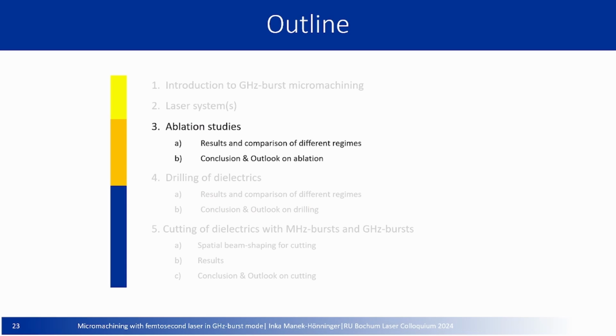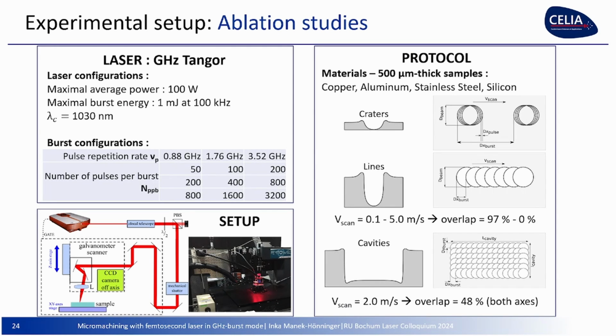Now, the ablation studies that help us to deduce what is happening, that I showed you in the introduction. So the laser system is this gigahertz Tangor. The setup is we go into a machining station. Here is a galvo scanner and the f-theta lens, and then we put the sample here. Everything is, of course, on a granite gantry for stabilization. The study that we did is with craters, lines with a certain overlap. We also studied the overlap. The influence was not that much. And cavity milling with an overlap of 48% in both directions: the direction where you move, and then also what we call the hatch.